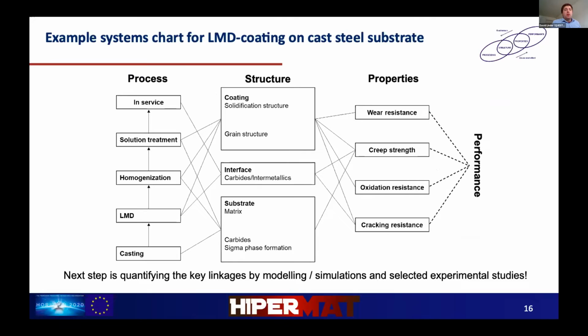So that's only looking into the casting of the steel, but if we look into the more complex process of adding an LMD layer on top of this, and then potentially heat treating it otherwise, and then seeing the effect on the final performance, we outline a systems chart highlighting the process structure and property relations, and I've been working on identifying different microstructural features that could be expected to be critical for the actual properties and the performance. So all of these are quite complex, with the substrate that behaves in a certain way, we have the coating that behaves in its own way, and then we have the interface where we might be seeing formation of different carbides or intermetallics, etc., during the coating process, but also in service.